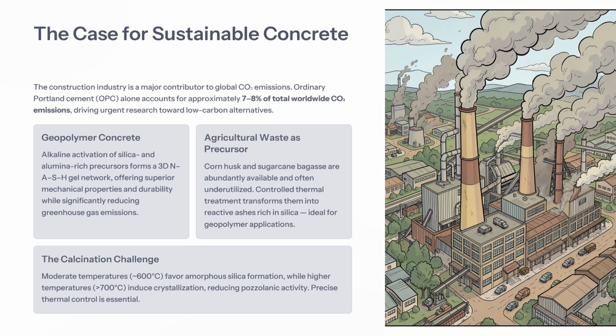Agricultural waste as a precursor: corn husk and sugarcane bagasse are abundantly available and often underutilized. Controlled thermal treatment transforms them into reactive ashes rich in silica, ideal for geopolymer applications. The calcination challenge: moderate temperature, around 600 centigrade, favors amorphous silica formation, while higher temperatures above 700 centigrade induce crystallization, reducing pozzolanic activity. Precise thermal control is essential.